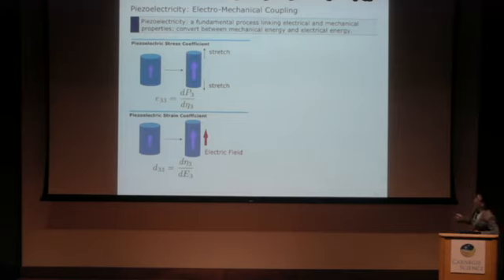So piezoelectricity is characterized by the piezoelectric coefficients. In this presentation, I will mainly focus on the longitudinal response, which is the response along the polar axis. There are two piezoelectric coefficients. One is e33, which relates the change in polarization to the change in strain. Another one is d33, which reflects the strain change in response to an external electric field. And these two piezoelectric coefficients are related to each other through elastic compliance.